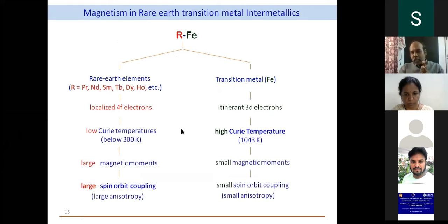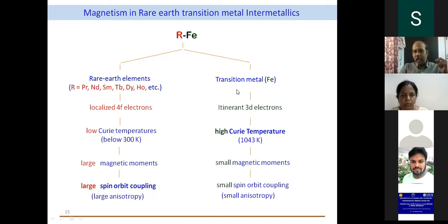Then we should also know why it is particularly this rare earth and transition metal. What is so great about these two? As we all know, the rare earths are Pr, Dy, Nd, Sm kind of elements, which are the lanthanide series, 4f elements, and the transition metals are iron, cobalt, and nickel. The magnetism coming from the rare earths is from localized 4f electrons, and it has a low Curie temperature, but the magnetic moments are large and the anisotropy is very high. For magnetostriction, as I told you earlier, the anisotropy has to be very high.